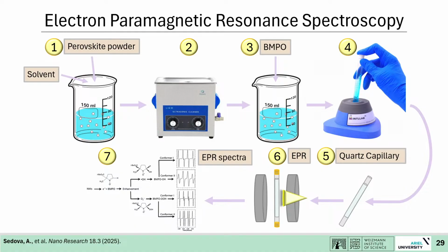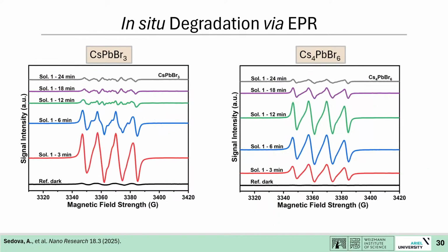And we measured the EPR spectra. So we were studying in situ degradation of halide perovskites such as CsPbBr3 and Cs4PbBr6. They're very efficient materials optically, nonetheless they're very sensitive to the environment, to polar solvents, if they're exposed too long to the light.